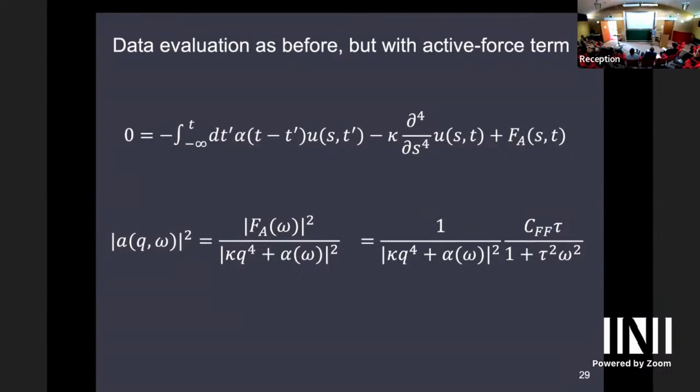And then we go back to the results I showed you from the cells, Alex and Fred's model, where we have seen that this force spectrum for these distributed dipoles is basically a Lorentzian. And it has this correlation time, which is 5 to 10 seconds. And of course, it has an unknown amplitude that we have to fit, we have to get out of the data. But we use this functional form as an assumption here in this method to get at the microtubules.